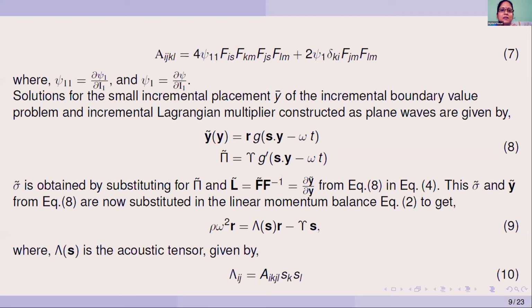And the solution for this incremental initial boundary value problem in the form of traveling plane waves is as given by this equation 8, as shown here for incremental displacement vector y tilde and incremental Lagrange multiplier pi tilde. Here this g is a function of argument s dot y minus omega t, where omega is the wave speed of the superimposed wave, and s is the unit vector in the direction of the wave propagation, and this r is the unit vector in the direction of wave polarization.